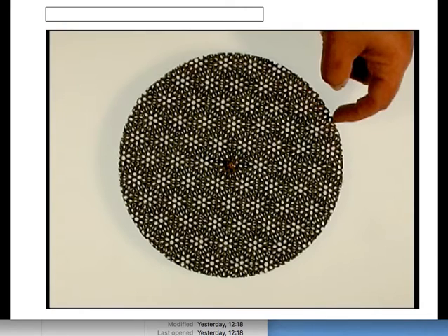So it's possible at certain misorientations to get perfect matching at a fraction of the lattice points. And those matching lattice points actually form a pattern by themselves, which we'll call a coincidence site lattice, or CSL for short. And of course, if we get good matching, then the properties of the boundary will also be different at those points. For example, we regard boundaries as easy diffusion paths, right? But if you've got good matching, there won't be easy diffusion paths. So at those orientations, you will actually get a dramatic decrease in the diffusion coefficient in the boundary and other properties as well.